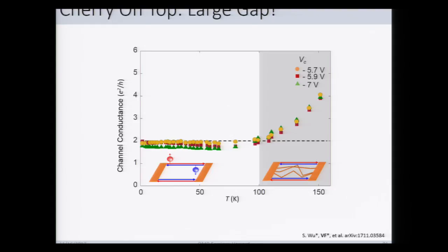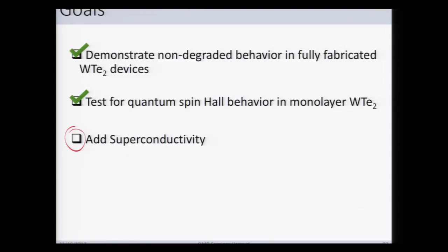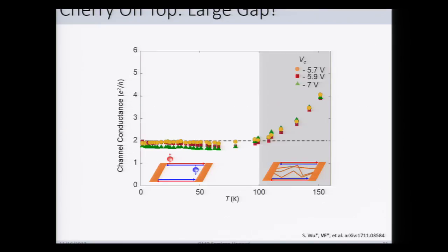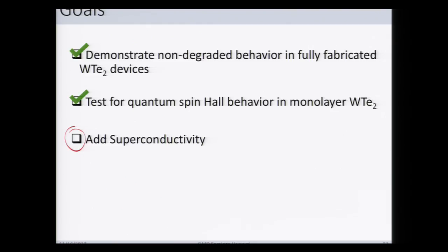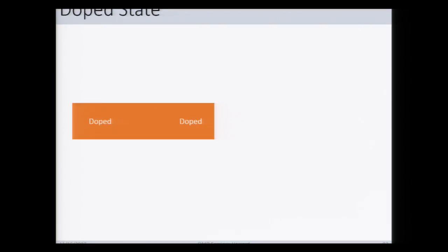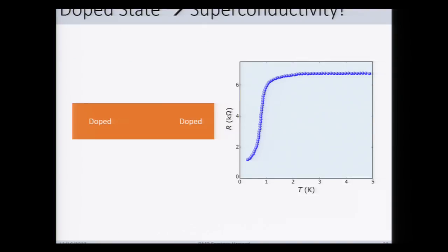Okay. So finally, we wanted to add superconductivity and try and do perhaps a proximity effect study on these edge modes. But nature threw us a bone that required us to do a bit of different investigation. Imagine that we have the same device, and in fact, it was the same device that I've been showing you over the past 10 minutes or so, but now completely doped with no depleted region in the sample. And we simply took this thing to lower temperature, and we found that the resistance drops starting around 1 Kelvin and going down by about a factor of 6 on this device.